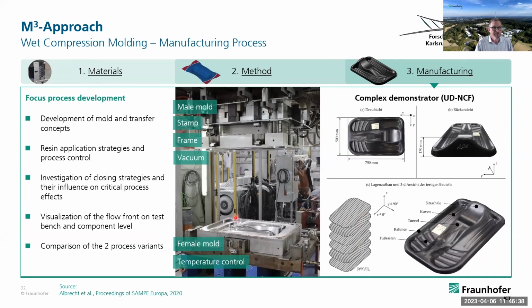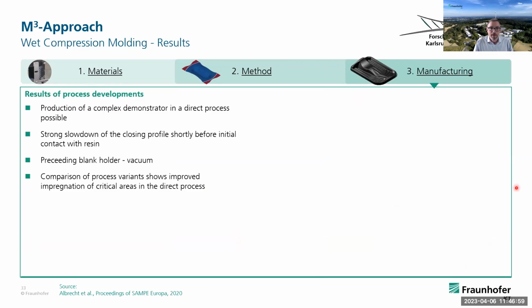And we developed, based on those results, the mold and the transfer concept, the resin application strategy and the process control, and we investigated the closing strategies and their influence on the critical process. And then basically compare the two variants, one direct form and the second one with a preform. And that's what you find here.